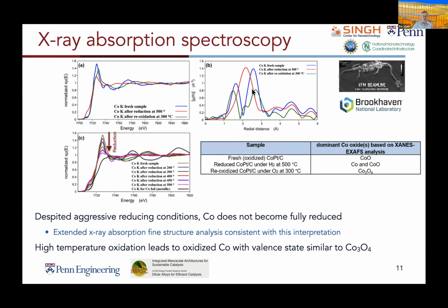And this is, again, consistent with the so-called extended X-ray absorption fine structure. With extended absorption fine structure, you look at the information past the edge, and you go through a series of fits that you can use to find out bond length, for example. What we were able to see is that on average, as we do a reduction, we get something that has both metallic cobalt as well as cobalt oxide, CoO. But if we then look at the oxidation thereafter, it changes to a very different form, which is Co3O4. So these are the sorts of information that one can obtain using X-ray absorption, which samples a large number of particles in the reaction environment.